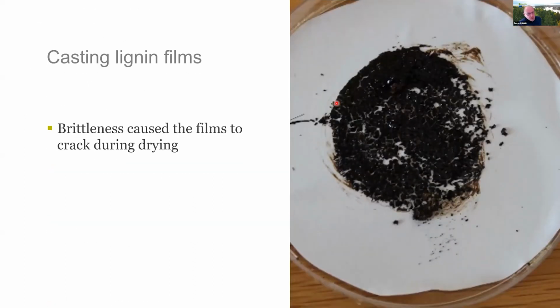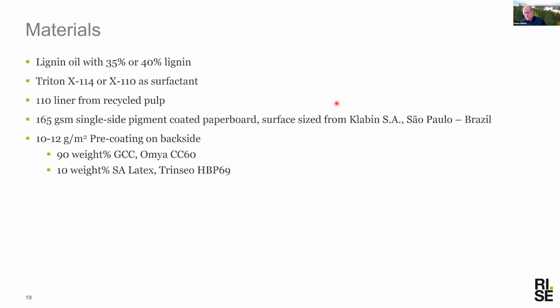We also tried to cast lignin films, and most of them ended up like this. Well, one of the problems is that lignin is quite brittle in itself. The other one is to make it dispersed in water, of course, in order to make it film forming. You need both of these, and we didn't get that when we tried to cast this particular one. So what we started to look at was lignin oils.